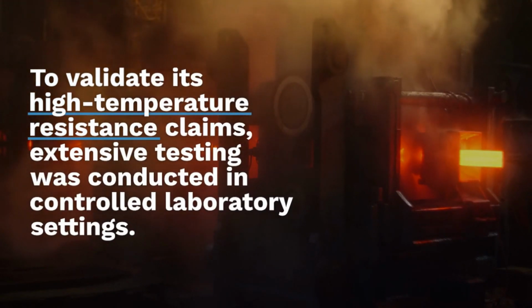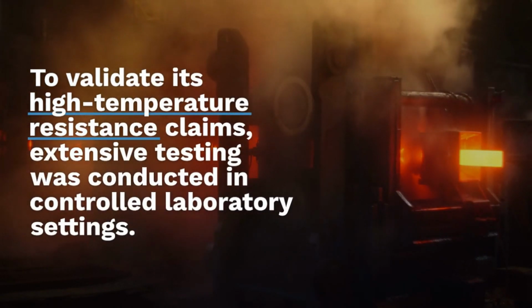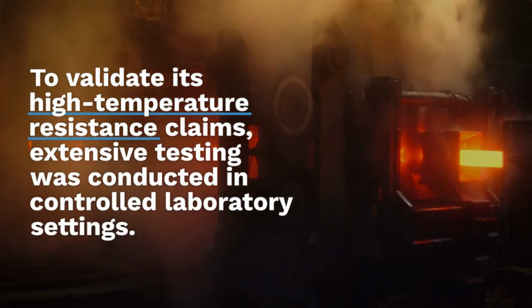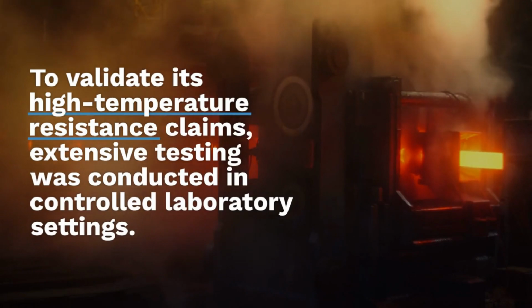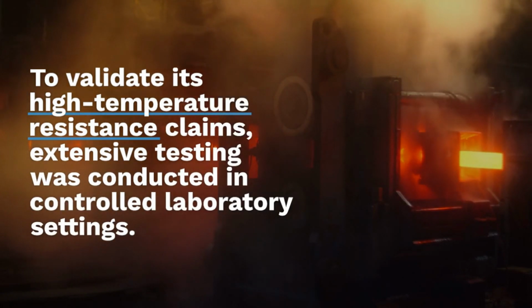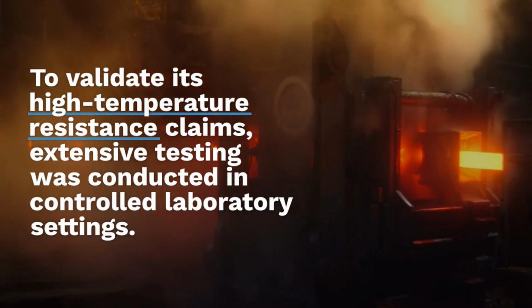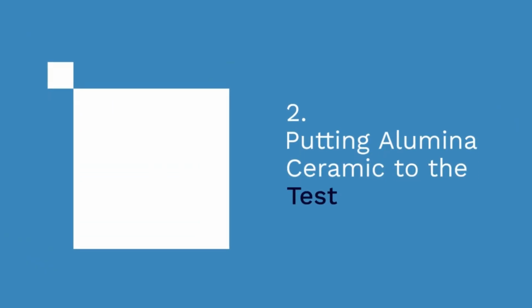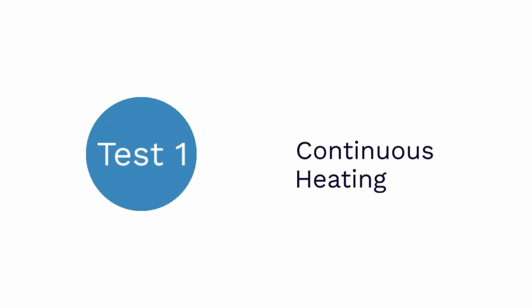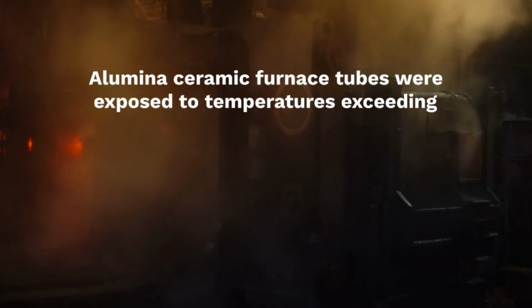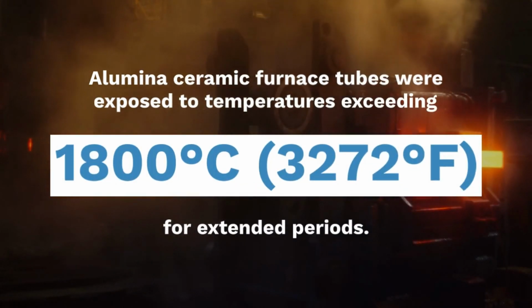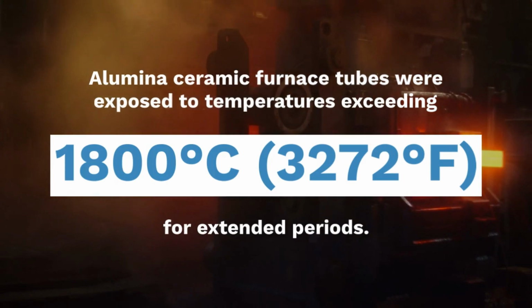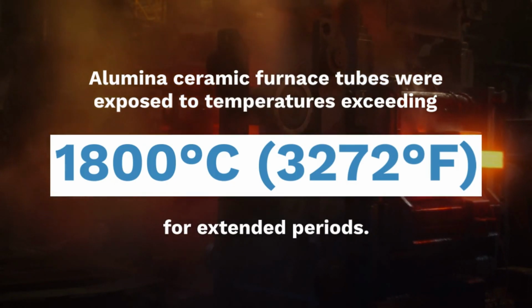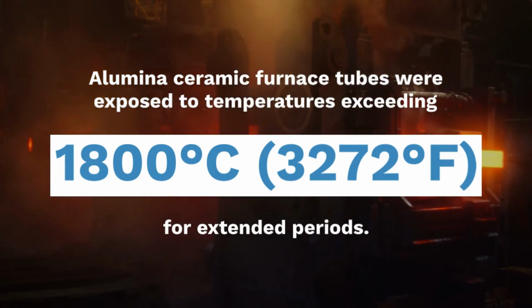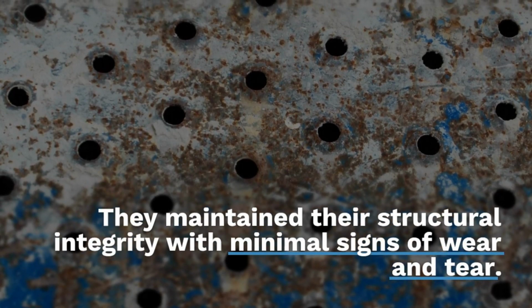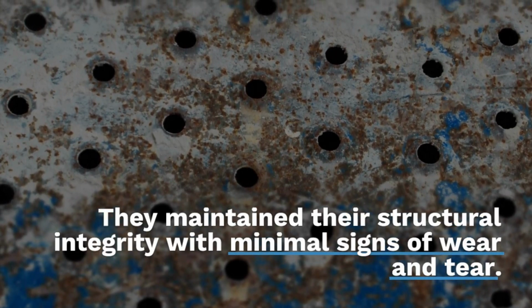To validate the claims of alumina ceramic furnace tubes' high-temperature resistance, extensive testing was conducted in controlled laboratory settings. These tests aimed to simulate real-world industrial conditions and assess the performance of alumina ceramic under extreme heat. Alumina ceramic furnace tubes were exposed to temperatures exceeding 1,800 degrees Celsius, 3,272 degrees Fahrenheit, for extended periods. The tubes not only maintained their structural integrity but also showed minimal signs of wear and tear.